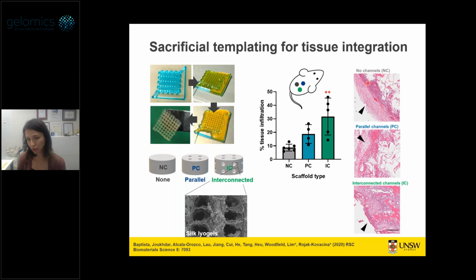So with our no channel scaffolds, even though they have porosity, we were getting a little bit of tissue ingrowth into the periphery of the scaffold, but the scaffold was also getting encapsulated by this fibrotic capsule. And this is not unusual. A lot of materials, when you implant them in the body, this is a typical response, right? Macrophages cannot phagocytose these materials because they're very, very large. And so the body encapsulates them in layers of fibroblasts and collagen to isolate that material as a foreign body. With our parallel channel scaffolds, we're getting more tissue ingrowth and a little bit of a thinner fibrous encapsulation response, but it was still there.